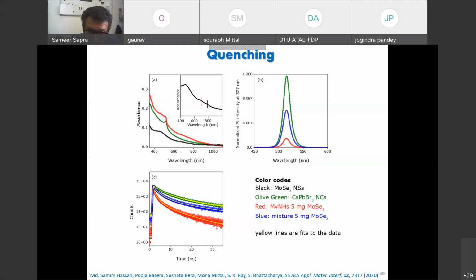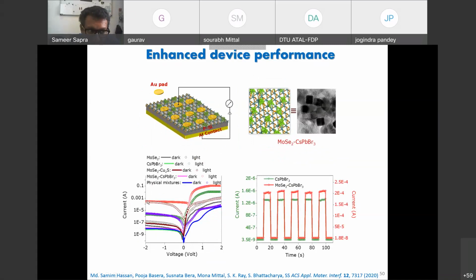Okay. And again, we tried to make these photoconductivity devices. And the very nice thing with cesium lead bromide is that these curves are very, very flat. So even at a small voltage, you can do your detection. For cuprous sulfide, you had to come to about 2 volts. But here, even at very small voltage, you could do your measurements. Also, for cuprous sulfide, the on-off difference was about 4,000. Here, the on-off difference is about 20,000. Okay, so you have much more gain in these cases.